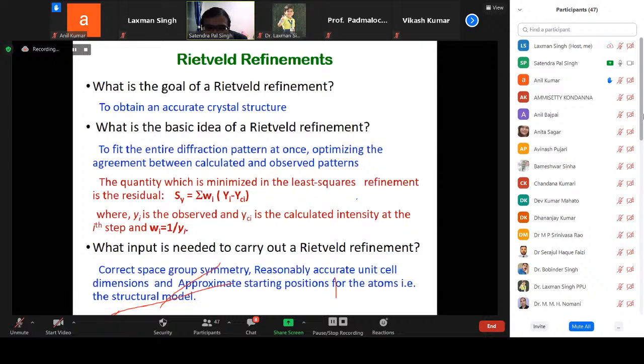We have to do the Rietveld refinement. The goal of the Rietveld refinement is to obtain an accurate crystal structure. What is the basic idea? To fit the entire diffraction pattern at once. What do we have to optimize? The agreement between the calculated and the observed pattern. That means Rietveld refinement will generate a calculated pattern based upon your given initial model, and it will try to optimize it against the observed XRD pattern. The quantity minimized is the least square refinement residual Sy, given by this symbol.